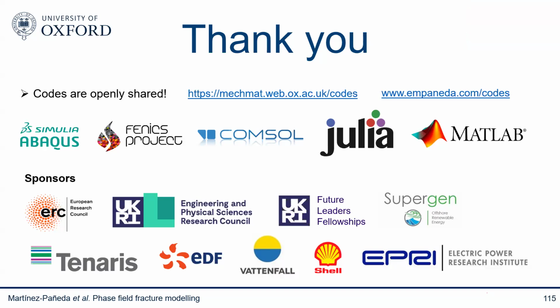I see. Thank you. On the phase field, there's a very nice paper by Lallit Anand from MIT showing with a similar model like these phase field models that you can capture those size effects. So you could input that constant material property, but see different sort of fracture behavior as you change the shape of your material, because you naturally capture how the fracture process interacts with the geometry. Yeah, I see. Thank you, Professor.